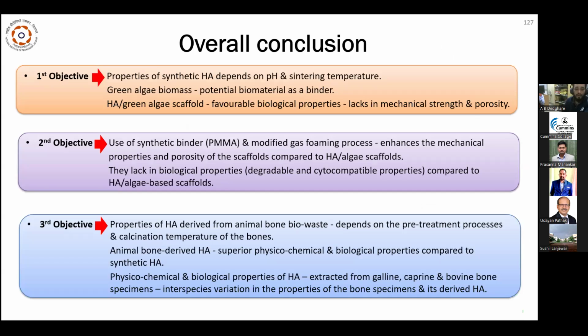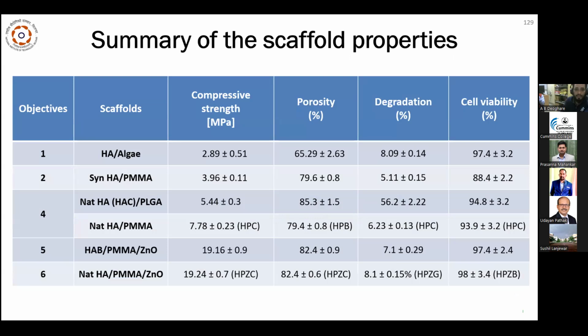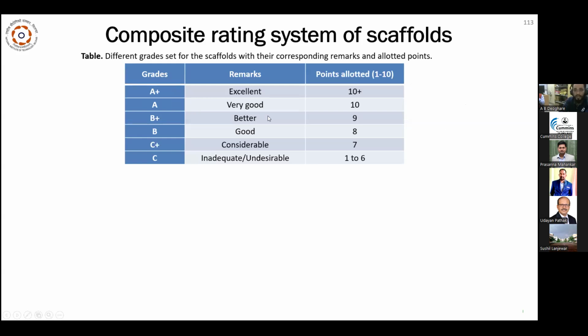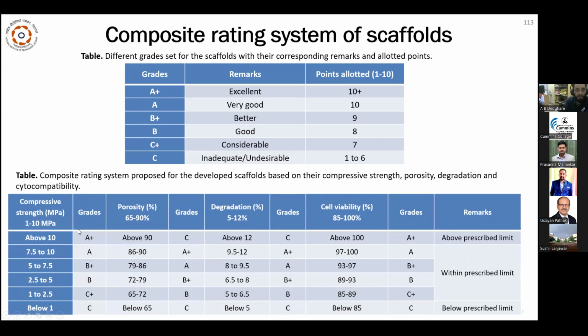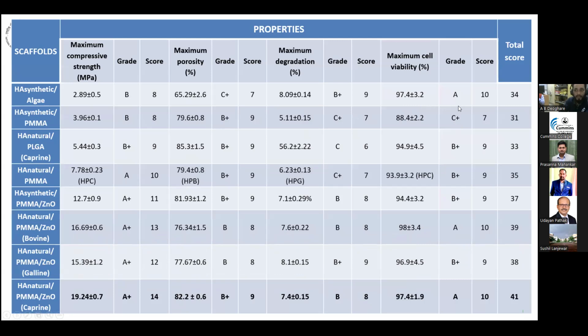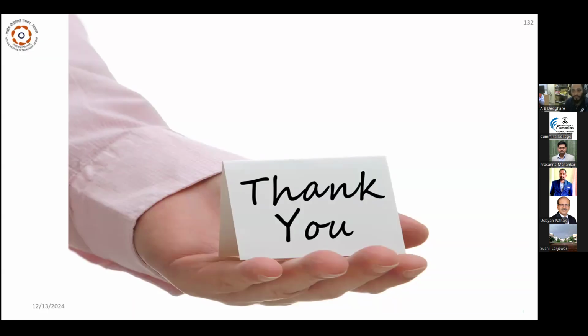From the overall analysis, some conclusions are drawn for the different objectives. In the summary of the analysis, for the different composite scaffolds, the compressive strength, porosity, degradation, and cell viability are compared, and then ratings are given. Different ratings are provided for each particular characterization, and from the overall analysis it can be concluded that the hydroxyapatite synthesized from the caprine bone, incorporated in the composite scaffold with PMMA and zinc oxide, gives the highest total score. So it is the best result from the above analysis. Thank you. What are the questions?